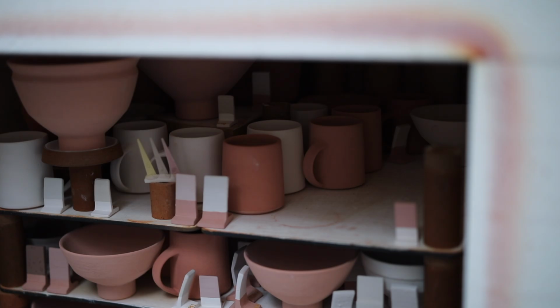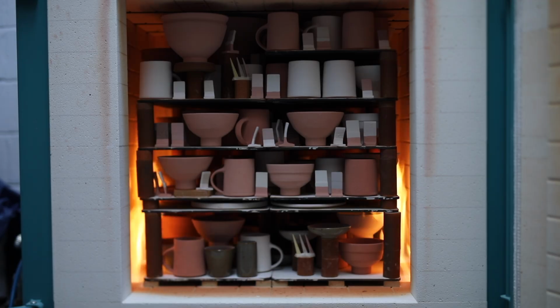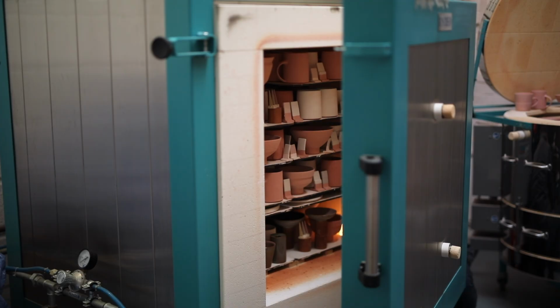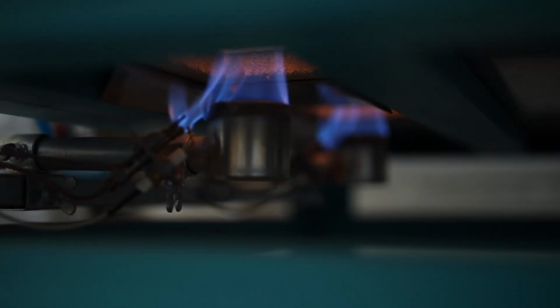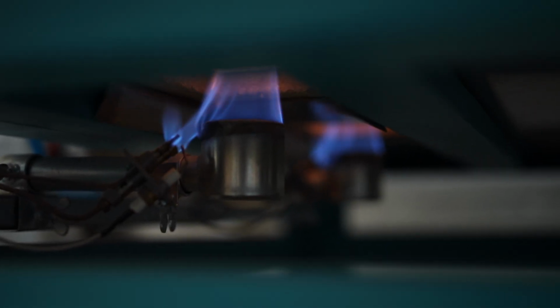If instead I fired the same pot in an oxidised atmosphere, in an electric kiln, the green colour would instead turn yellow. And the surface of the pots would also have less interest overall, because as the oxygen is stripped away from the clay and glazes, it also brings some of the iron with it, which bubbles to the surface and melts into these lovely metallic dots.